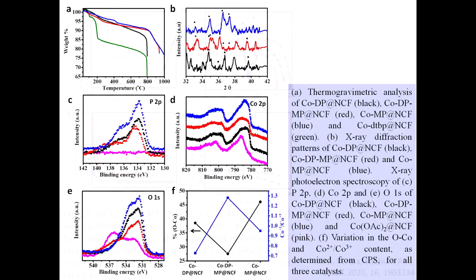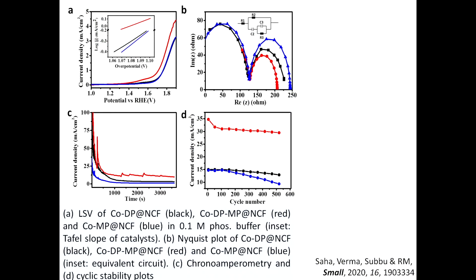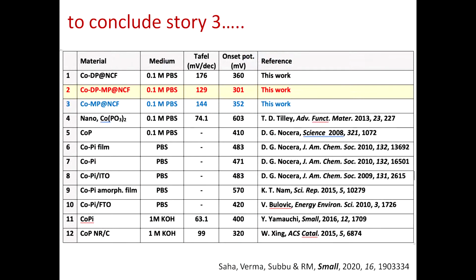I think this paper actually got accepted within 3 days of submission in Small, with some wonderful comments, because Daniel Nocera started this about 10 to 12 years ago, and a lot of people are trying to figure out which phosphate, the meta, pyro, ortho, or dihydrogen phosphate, is the most active form. So it turns out that you need to have Brønsted acidity as well as the metaphosphate for promotion of cobalt 2 to cobalt 3, which is a very important stage. Okay, at the point of time when we published this, pretty much it remains still the same.